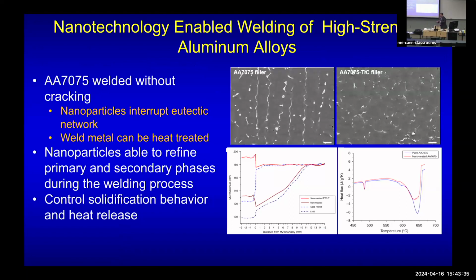And here, with the nanoparticles, you can see that without nanoparticles there is always a continuous phase and also a lot of hot cracking. With nanoparticles, it is much more dispersed. By this way we can really eliminate hot cracking and make the performance much better. Also, because we use the same filler metal. For example, in the automobile industry, mostly we want to use 6061 or 5083. So we must use dissimilar welding rods, with different chemistry, to avoid hot cracking during welding. So you shift the chemistry away to a safe zone.